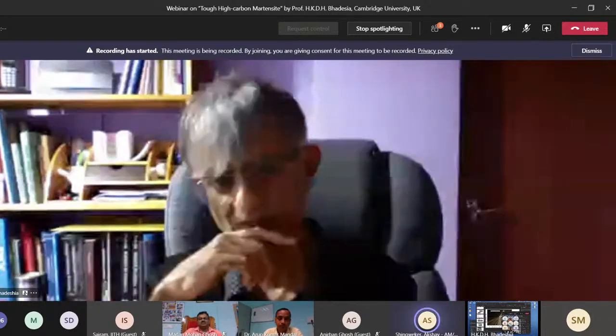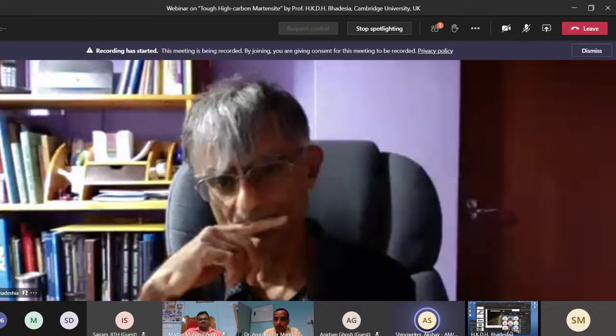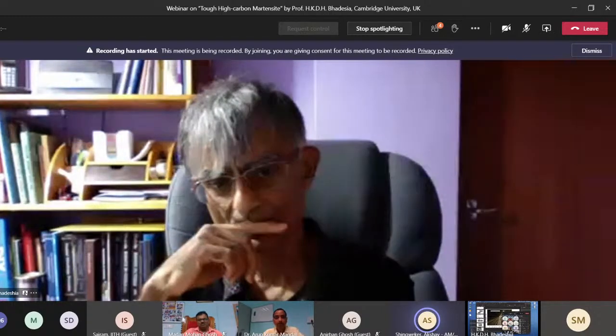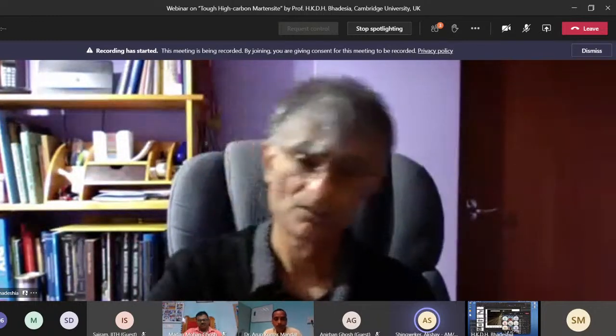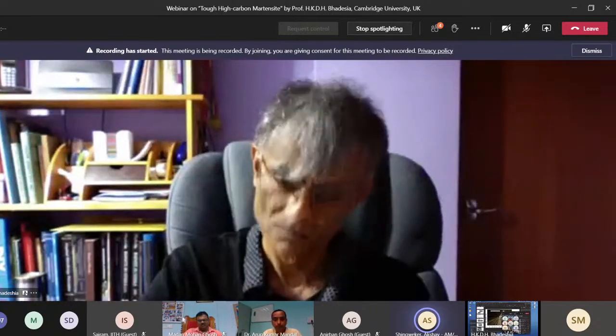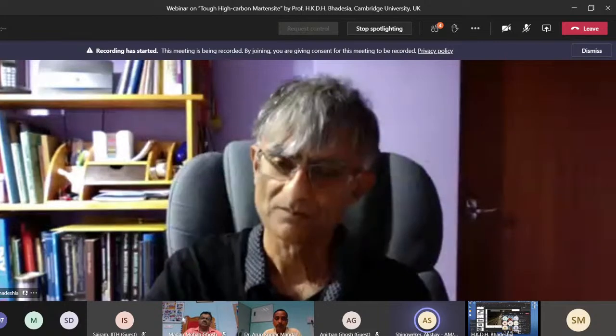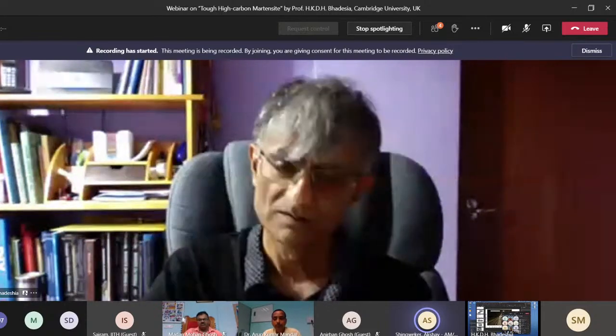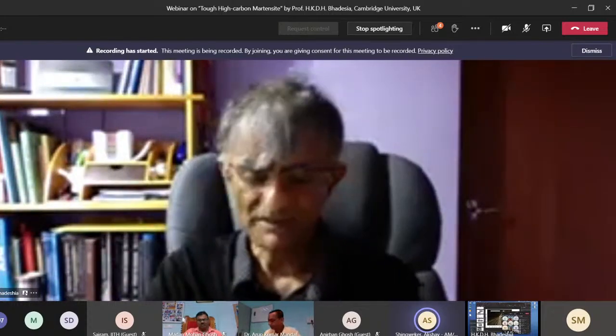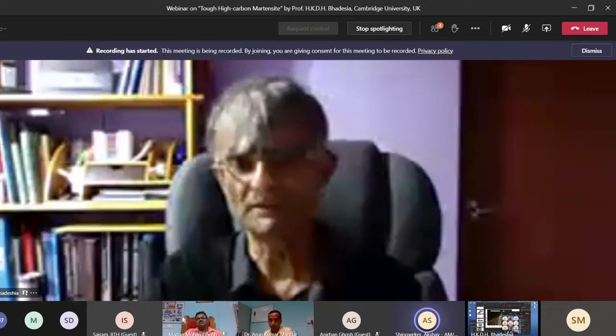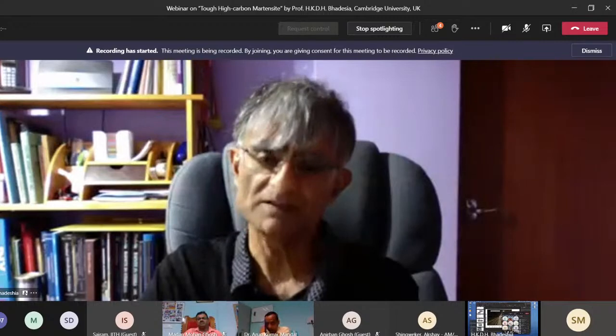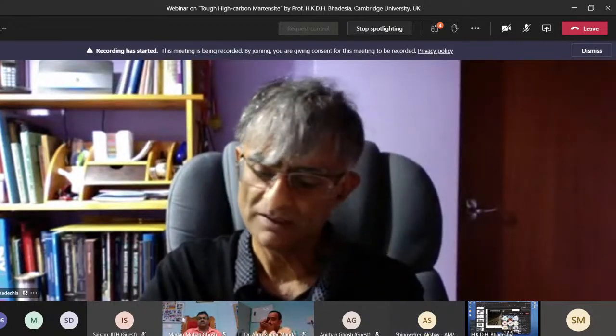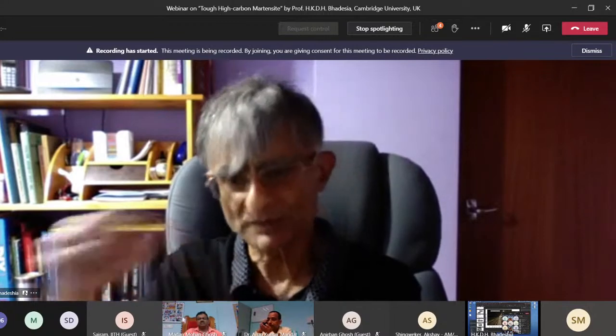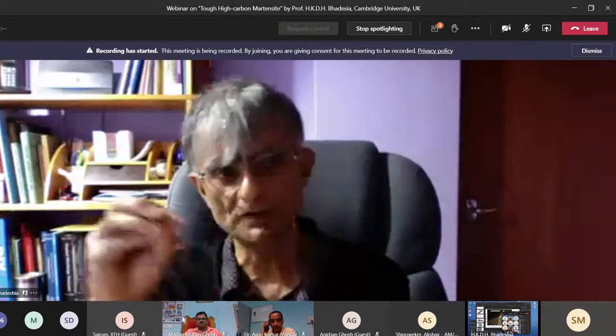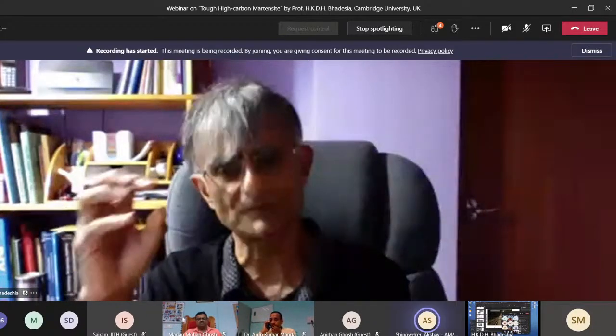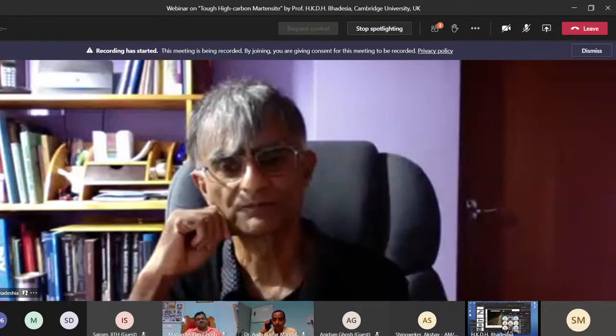Yes, sir. I just wanted to request you to put more light on the shape and the size of retained austenite in martensite. Normally, when it forms as a thin film or block, which would be a better choice to have better ductility, with smaller block size and pocket size? Yes. Basically, you want fine austenite. Even if it is blocky, if it is very fine, then that has good properties. And films are ideal, but you can't always get them. So in the assisted steel that I showed, they were more like blocks, but they were very fine blocks, so it doesn't matter. But if you have coarse blocks, then you get poor toughness.